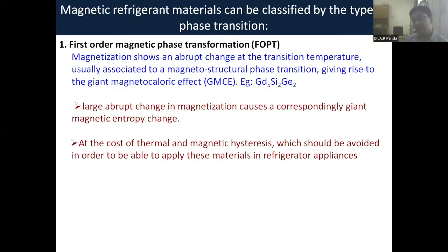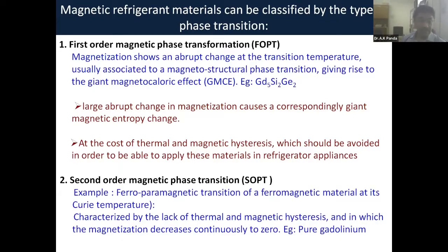Now there comes the role of tailoring the composition, and you do away with the magnetic hysteresis, because magnetic hysteresis is something you would not desire when we make magnetic devices or magnetic refrigeration systems, because if your cooling cycle shifts every now and then, that is not desirable. Now there is the second order magnetic phase transformation, a ferro-para transition, and this doesn't involve two complexes. We do not find much magnetostructural transformation, and what happens is that it is like a ferro-para transition at a Curie temperature, and the moment goes gradually to zero, typically like gadolinium, pure gadolinium. In fact, this has been used for many thermal calibration systems.